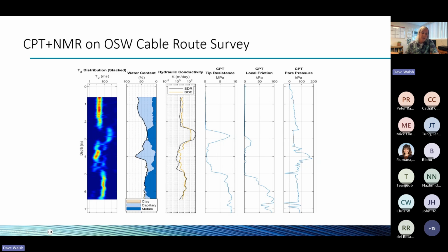So this sand unit has a lower porosity. See that 30%? Whereas this one's more like 40%. So this one actually has a higher density. And it's also coarser. These are much coarser sands. You can see that from the relaxation times. That's a pretty long relaxation time compared to this down here. And up in these soft sediments, you've got more like 60% porosity. Previous site, 50%. And then in between these two sand units, you've got a very high porosity data point right there at about 70%. So it's very soft, very watery material right there.